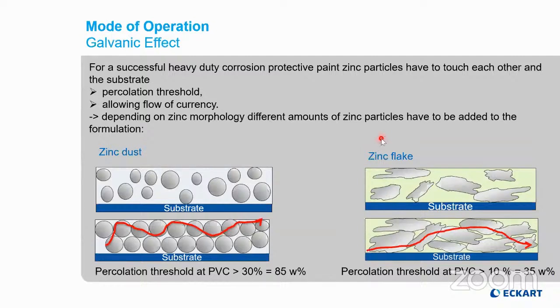I mentioned already in the beginning that corrosion protection only occurs when a flow of electrons is possible. And the flow of electrons can occur, and zinc can work as a galvanic corrosion protective pigment, when there is a flow of electrons. A flow of electrons can only occur when the particles get in touch with each other, and through the contact point, electrons or current can flow.